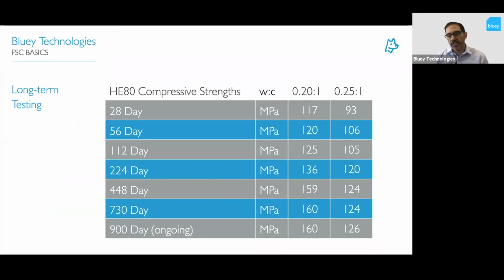As you can see, just tabulated the strengths. The testing was completed both at 0.2 and 0.25, so we went the high end and low end water ratios, and you can see that we've got strength gain all the way through to the 900 days. That testing is still ongoing. We know there are no changes now, but we still would like to keep testing that, and we're about 5 years into that process.